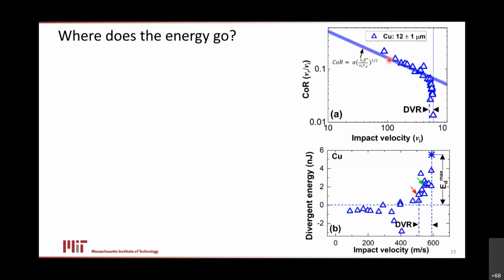If you look at these data, everything that does not fall on the plasticity line is telling you that there's an excess softening going on. So you're pulling kinetic energy out of the particle. You're slowing it down more than plasticity alone would do, right? So that's what this tail is here. And you can actually quantitatively measure that energy, and we call that the divergent energy. And you can see here for copper on copper, that divergent energy is a few nanojoules and maybe as high as 5 or 6 nanojoules up to the critical bonding velocity here. So that's interesting. We've got 6 nanojoules worth of energy we've got to explain, and we've got to link that somehow to the process of bonding.